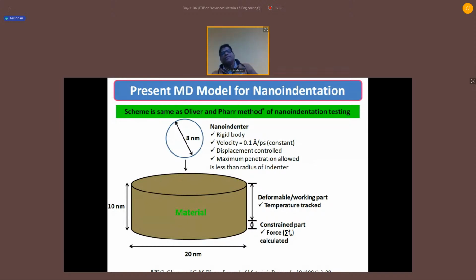The area calculation is different for the nanoindentation technique, because in tensile deformation we can calculate the percent elongation, Young modulus, and yield strength also. But from a simple indentation, we can predict material properties like hardness and Young modulus itself. So nanoindentation is a very versatile method. We are using single crystal analysis here, and another team in our lab is working on polycrystal. So the method is very versatile.